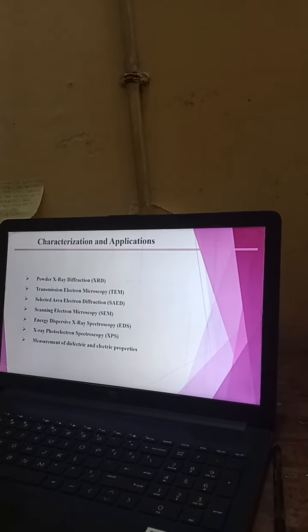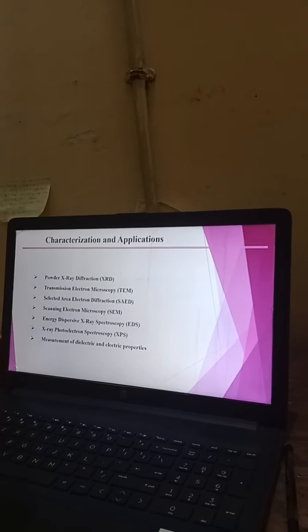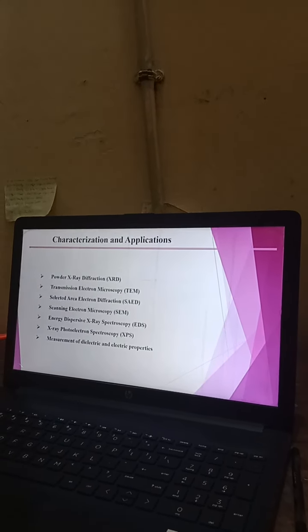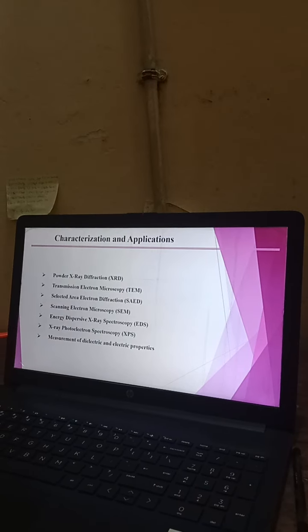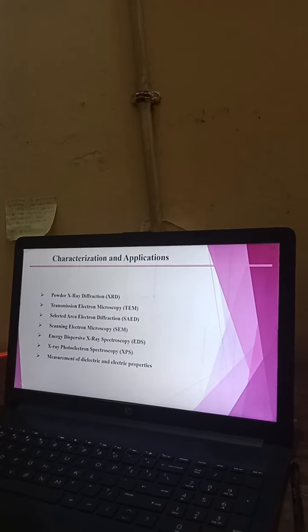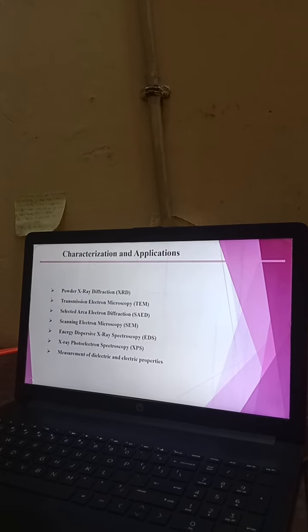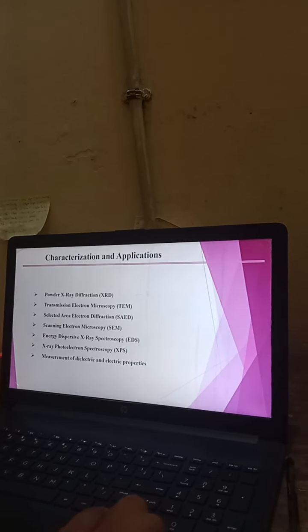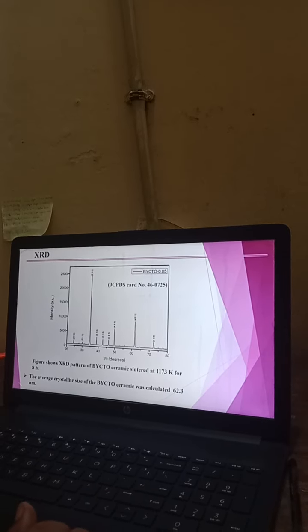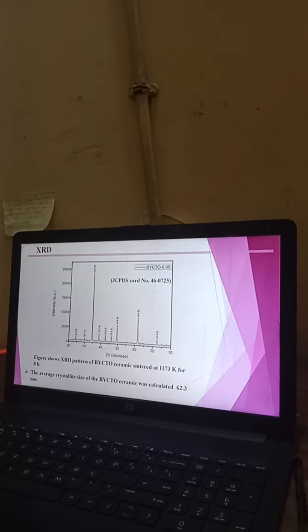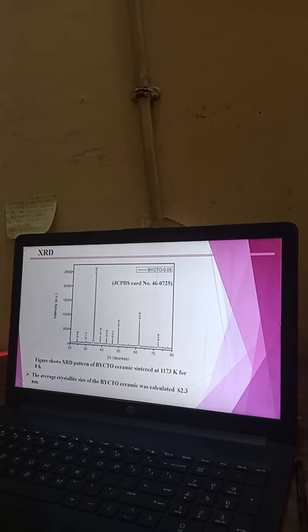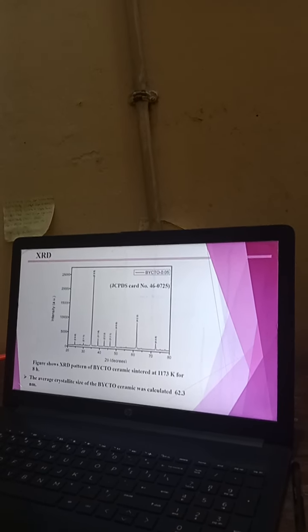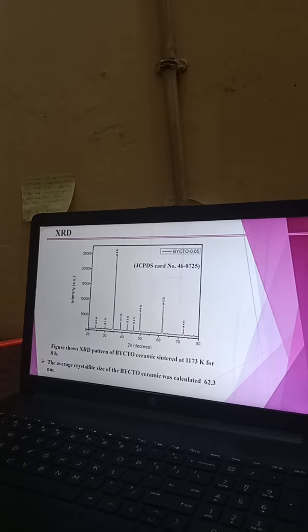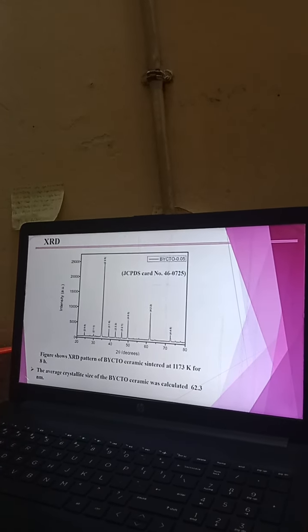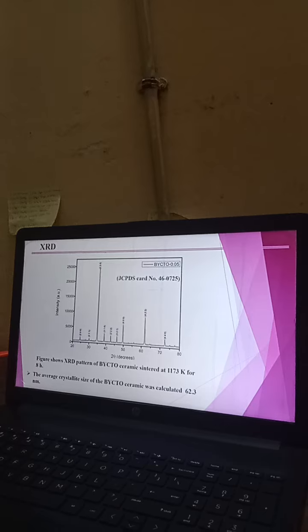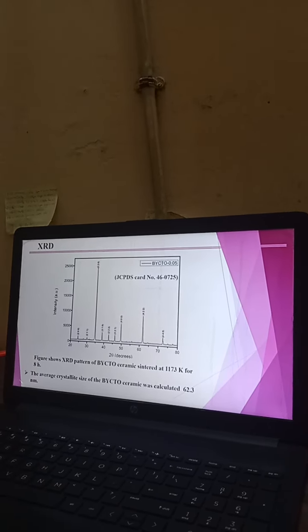That is transmission electron microscopy, selected area electron diffraction, scanning electron microscopy, energy dispersive X-ray spectroscopy, X-ray photoelectron spectroscopy, and last one is measurement of dielectric and electrical properties. The phase formation of the ceramic was also confirmed by the XRD pattern, where all the peaks were correctly matched with the JCPDS card number 460725.